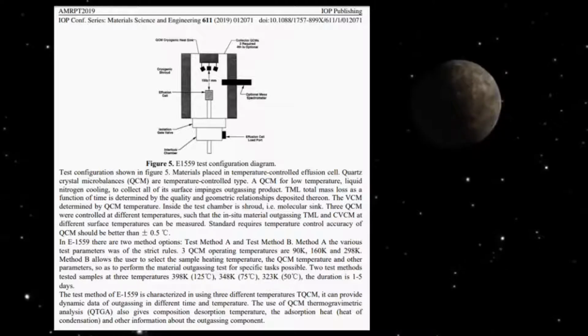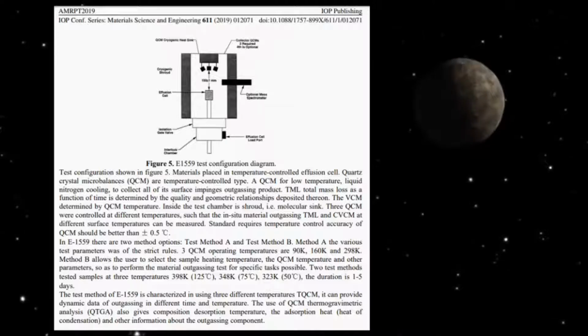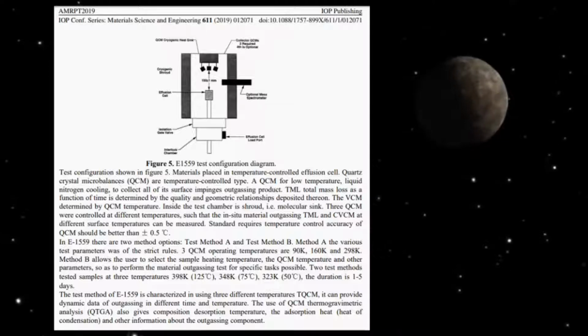The test method of E1559 is characterized by using three different TQCM temperatures. It can provide dynamic data of outgassing at different times and temperatures. The use of QCM thermogravimetric analysis, QTGA, also gives composition, desorption temperature, heat of adsorption, heat of condensation, and other information about the outgassing components.